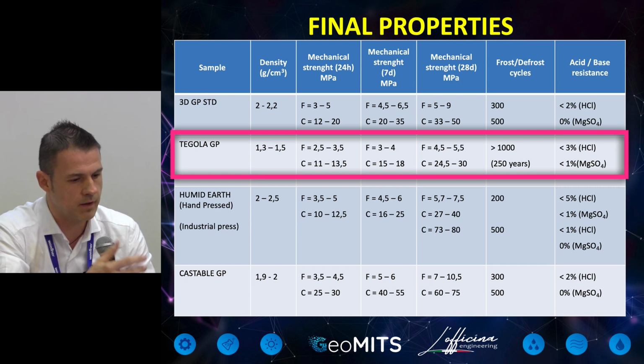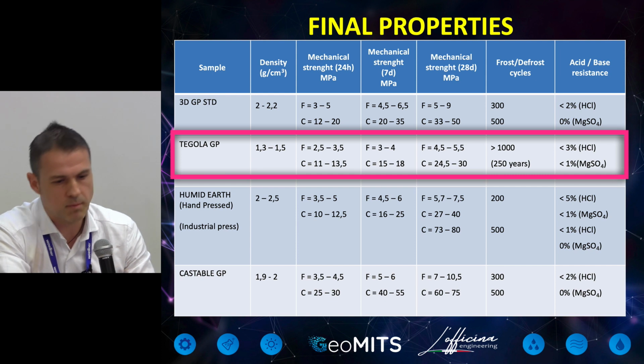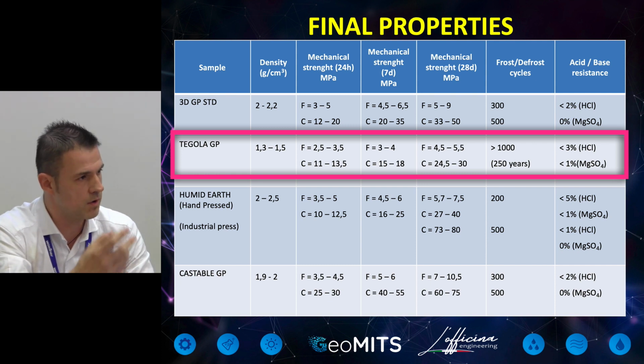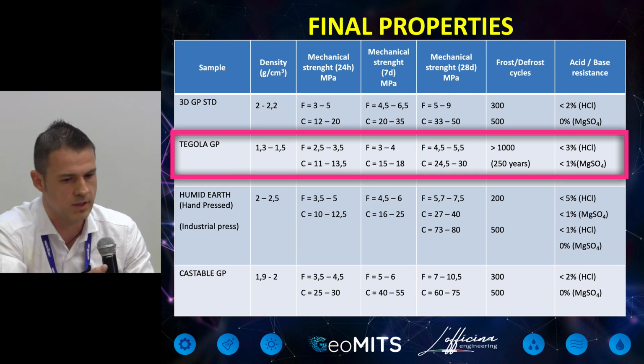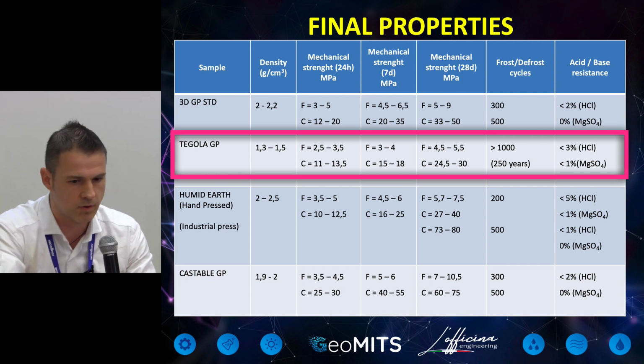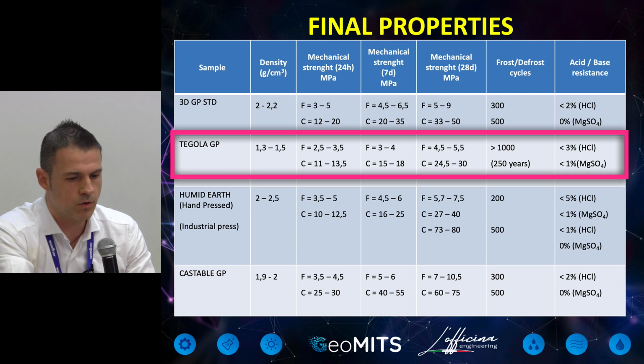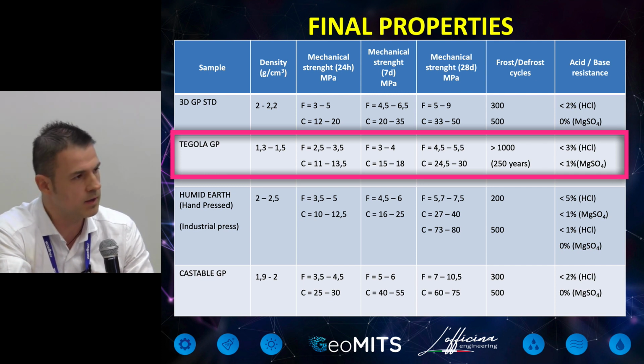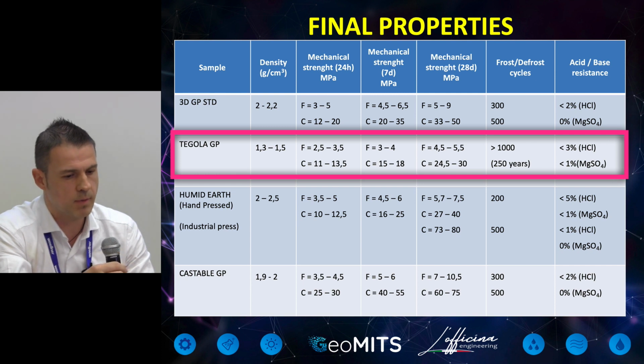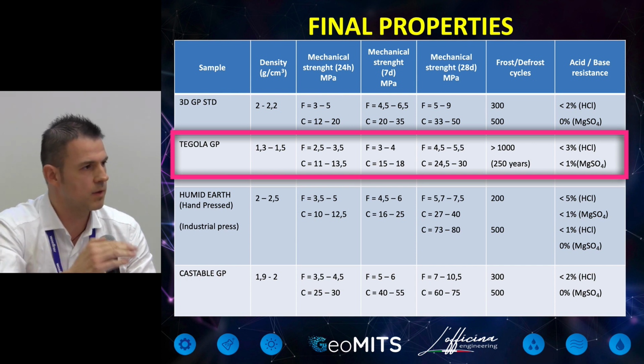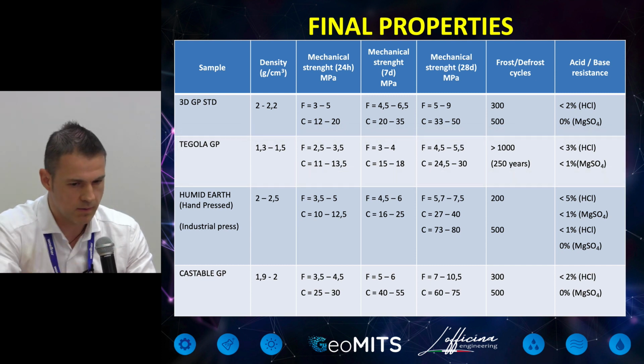And so I reduced the weight by 33%, but I passed all the parameters, and I passed more than 1,000 cycles, and they compared to years are 250 years. This is, I haven't done this test. The test was done for this roof tile manufacturer, and the final strength could go from 24.5 to 30 megapascal, depending on the fluidity, because this is a fluid material, but some manufacturers can manage only butter-like consistency, so with no water, and so they press with the rubber press elements.